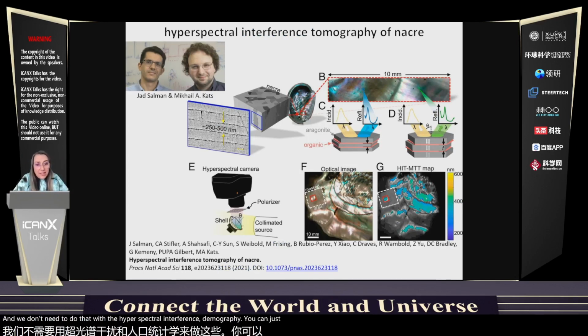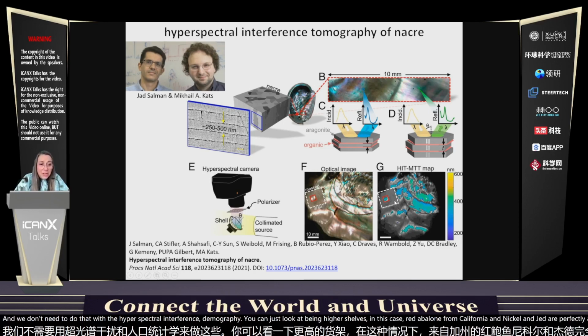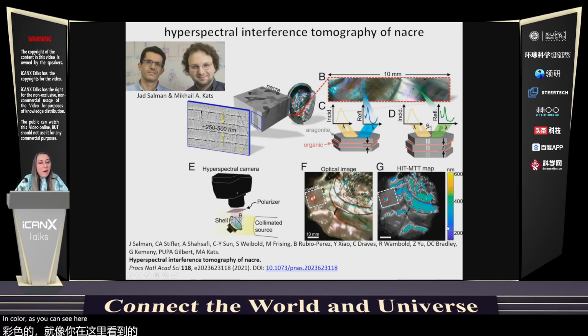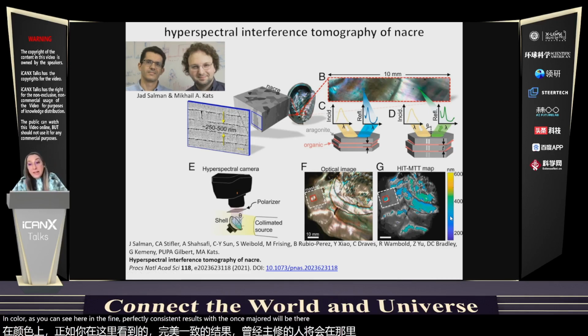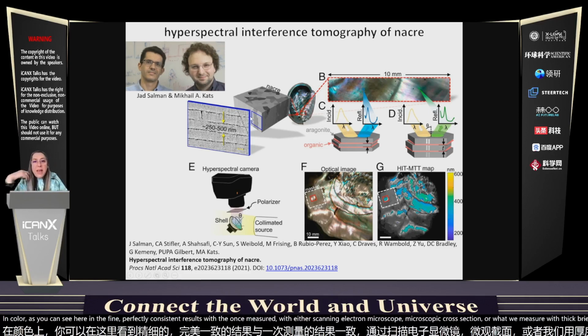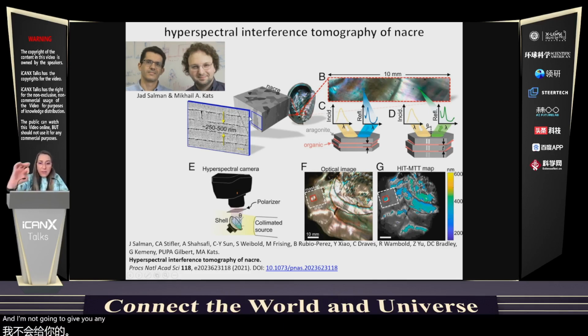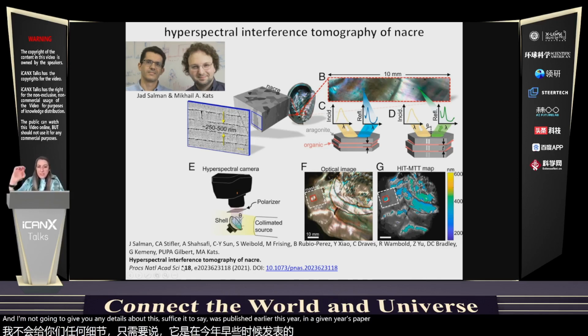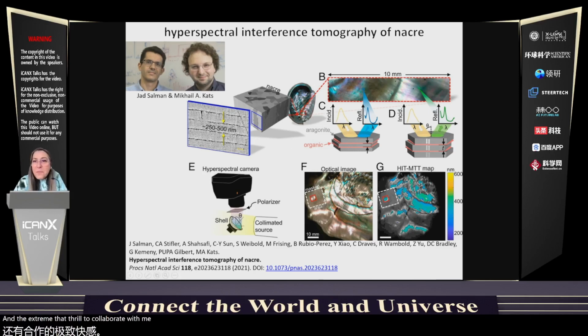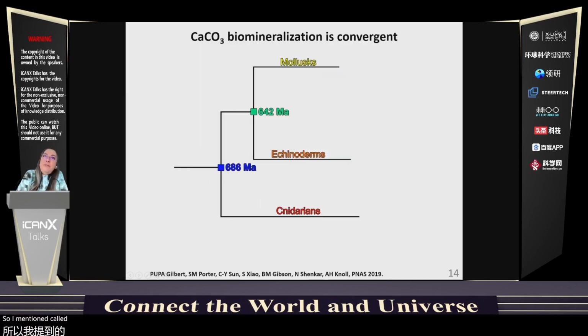You can just look at the entire shell, in this case from California, and Mikhail and Jad are perfectly able to measure the tablet thickness and display it in color, as you can see here, and they find results perfectly consistent with the ones measured with either scanning electron microscopy in a cross-section or with PIC mapping. I'm not going to give you any details about this. Suffice it to say, it was published earlier this year in a PNAS paper, and it's been a thrill to collaborate with Mikhail. So I mentioned convergent evolution of nacre.